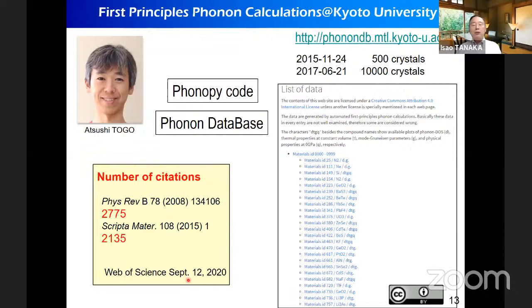We have been working on first principles phonon calculation for a number of years. My colleague, Professor Togo, is very good at coding, and he established the Phonopy code, which can be used for phonon calculation and attached to a first principles engine like VASP or other first principles codes. We also established a phonon database by this Phonopy calculation, and this code has been quite popular worldwide.